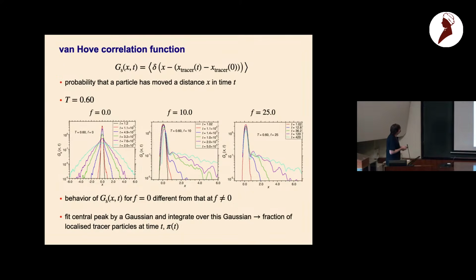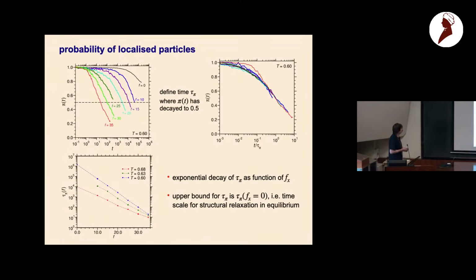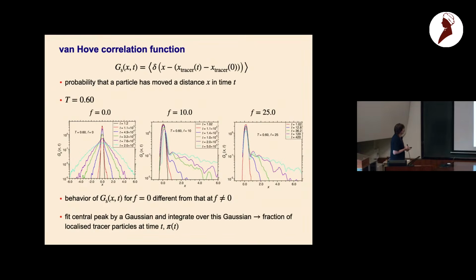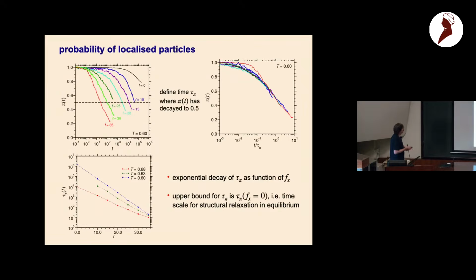Now one can do the opposite and determine the fraction of localized particles and how they decay as a function of time. We make fits with a Gauss function over the central peak and determine from this the fraction of localized tracer particles at time t, which we call pi of t. This is shown here - it's a decaying function, decaying slower the smaller the force is. We can read off a characteristic time scale, scale the curves with it, and then the different curves fall more or less on a master curve.